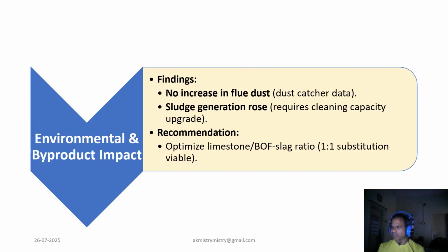Now coming to the environmental feedback of the trial. We can say that environmentally the trial was very encouraging. The flue dust level remained very stable. The sludge generation increased slightly, which suggests a need for enhanced cleaning capacity. The intricacies of the flue dust level and its hidden facts will be shared in the next presentation, as this would go very long. On the material side, we recommended a 1:1 limestone to BOF-slag substitution ratio to maintain basicity without overloading the system.